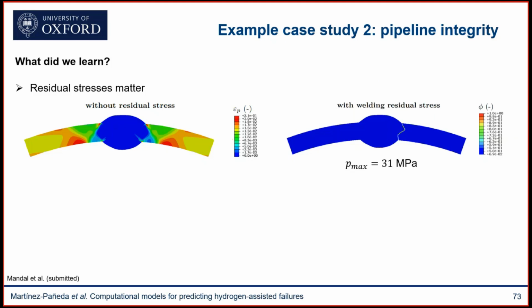Then we use the model to answer questions that we want to understand. The first one, for example, is whether residual stresses matter or not. We found that for the X52, residual stresses did not matter. This is a more ductile material, less susceptible to hydrogen embrittlement. And in both cases, with and without residual stresses, in the absence of defects, we found that the failure was due to plastic collapse. However, in the X80, which is a more brittle and susceptible material, we found that incorporating residual stresses made a change from this plastic collapse failure mechanism to this brittle cracking failure mechanism. And you can see this is attained at a pressure of 31 megapascals. So residual stresses can matter depending on your material and conditions.